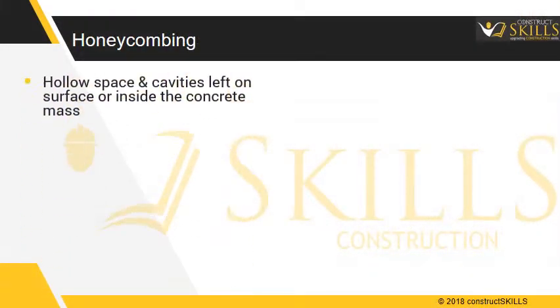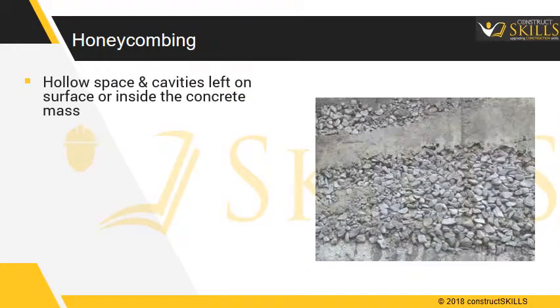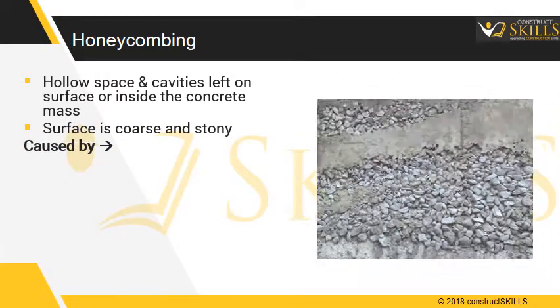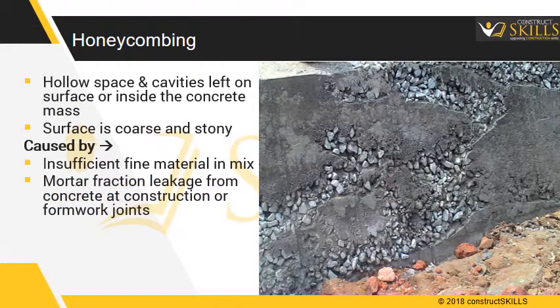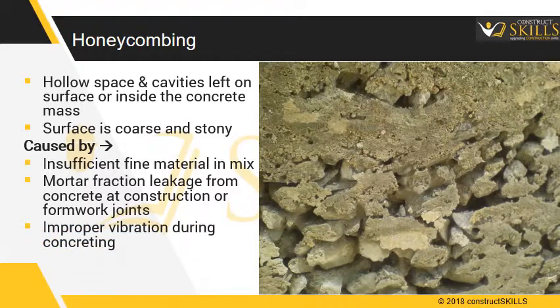Honeycombing is hollow space and cavities left on the surface or inside of the concrete mass. The surface is coarse and stony, which is a result of insufficient fine material in the mix, leakage of mortar fraction from the concrete at construction or formwork joints, and improper vibration during concreting or use of very stiff concrete.